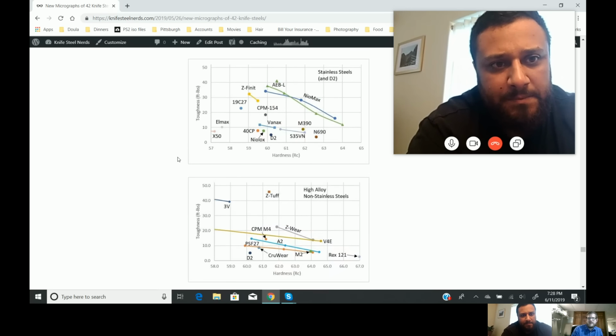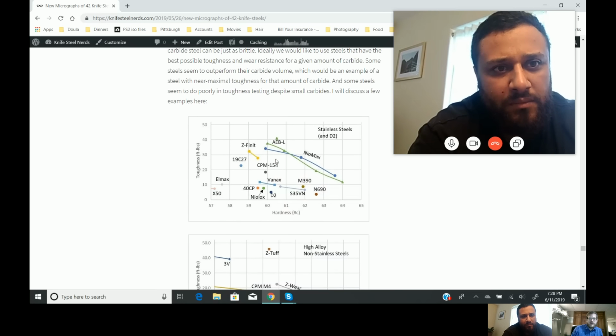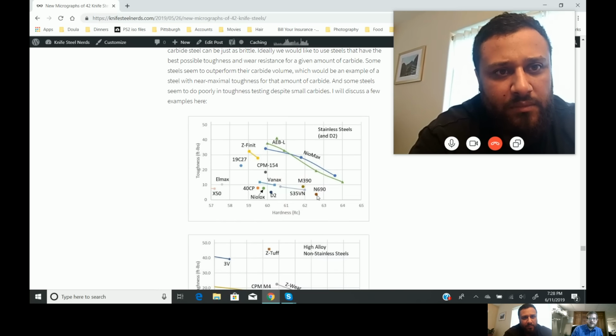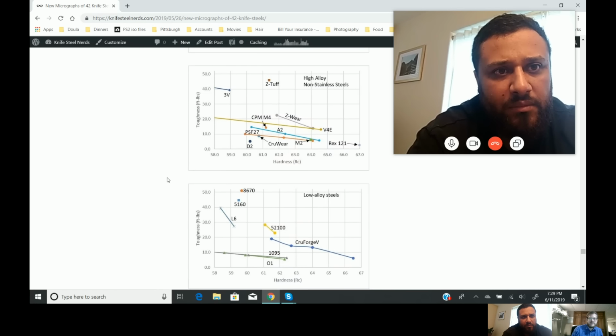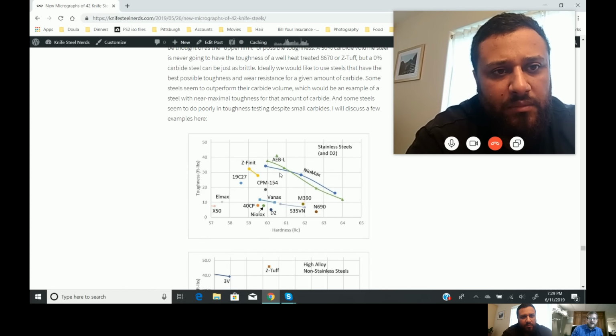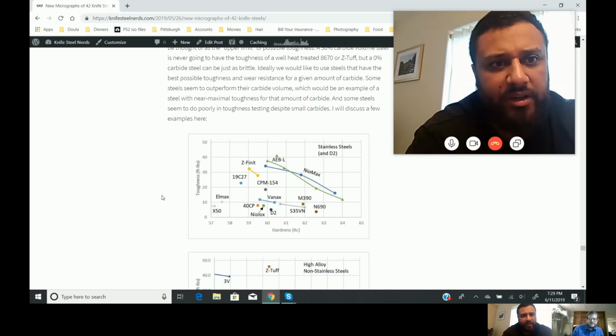And then stainless steels, we've got a big spread, from N690 with its big carbides. This is also relatively hard, so you'd think we could boost this toughness a little bit by going down in hardness. Versus the AEBL with really high toughness, basically as tough as any of the carbon steels, just about. Then NioMax, similar toughness, maybe a little tougher at higher hardness for some reason. Z-Finit is the LC200N Cronidur 30, also pretty high toughness. Yeah, that did good, actually. I'm surprised how good that did, the Z-Finit.